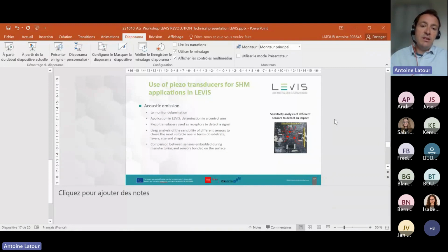In LEVIS, we focus first on the acoustic emission. We are using this technique to monitor some delamination in this project, and mainly in the control arm application. As I mentioned before, we use this printed piezo transducer as a receptor to detect the signal. So we are running a study to evaluate the sensitivity of different architectures of sensors developed at CINEA to choose the most suitable one in terms of substrate. I mentioned that we can use different kinds of substrates, but also number of stacked layers, and also the size and shape of the sensor.